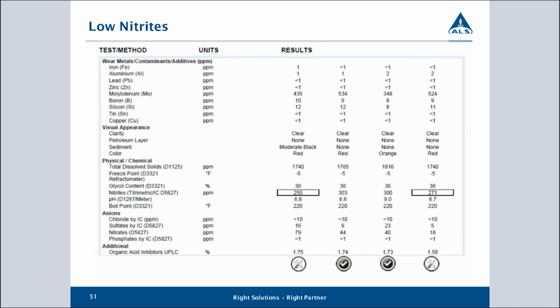We can see some black material is being deposited out. This could indicate that some sort of black oxides are present and some sort of corrosion is starting in the system. However, we're not really seeing much iron, so corrosion itself is probably relatively light at this stage. But if we keep running this coolant like this, we are likely to see an increase in corrosion over time. In this situation we really need to replenish this, so a drain and refill will probably solve this particular problem.